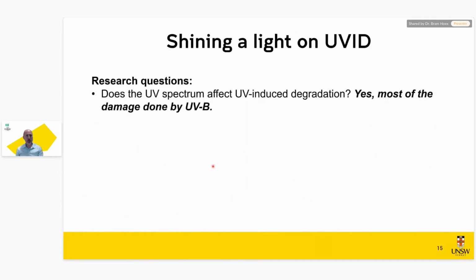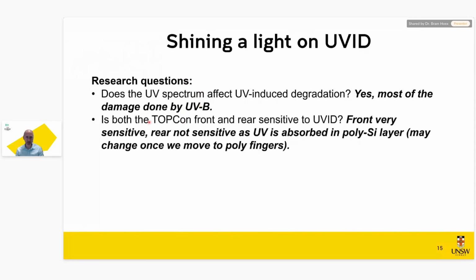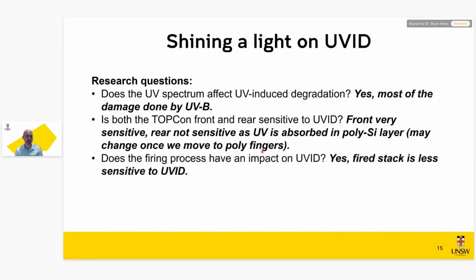So we've already had some answers to the initial questions I posed. Are all photons created equal? No. High energy photons create significantly more damage, and we're working on quantifying that even further. Do the TOPCon front and rear have the same sensitivity? No. The front is very sensitive, and that's why in the remainder of my presentation I will mainly focus on the front of the TOPCon solar cell. We will really narrow down on what's happening at that interface. The rear is not sensitive because all the UV is absorbed in the polysilicon. Details can be found in the paper. This will change if we go to poly fingers, because then the rear becomes sensitive again. Does the firing process have an impact? Yes. Firing makes your cells more stable to UVID. So it shows you one of the knobs we have to make the cells less UV sensitive.